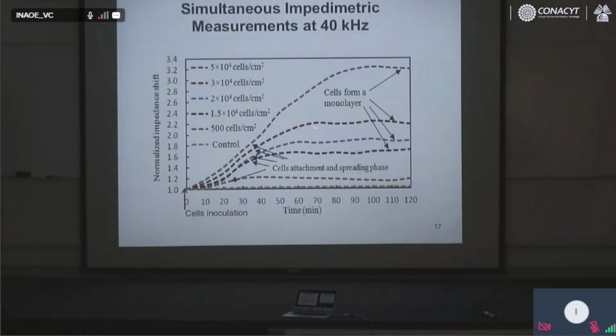Okay. Now here you can see the impedance value, and here is the time, and the impedance is getting like that. There is a little bit of fluctuation because the cells are not attached totally all the time, they move a little bit there. And the impedance is a function of the cell numbers. It's better to work with a high concentration of cells, because you will have more cells on the chip and you will have a high impedance.